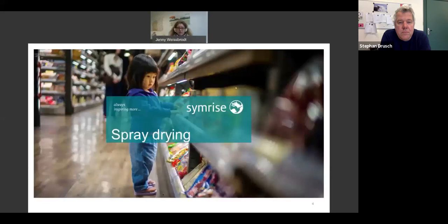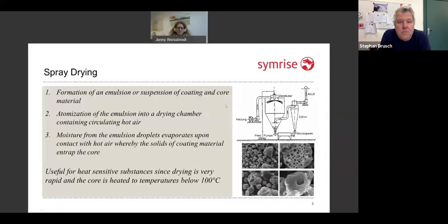So let's come to the spray drying. Spray drying, from the first view, is just a very simple process. It's just liquid in, powder out. Obviously, you can do a lot of mistakes during this processing. The first thing you should do is to prepare a proper emulsion or suspension of your active in your carrier material. Then this liquid is more or less atomized into the drying chamber, where it comes in contact with circulating hot air. The particles dry and can be harvested at the bottom of the spray drying tower as a dry powder.